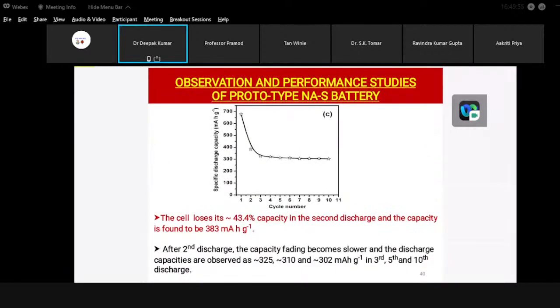What we observe is the cell loses almost 43% of the capacity in the second discharge, and subsequently it is around 383 milliampere hour per gram. However, after the first discharge, the capacity reduction is negligible. At the 10th cycle, we observed the capacity to be 302 milliampere hour per gram of the active material, which is again good enough for an electrolyte system.